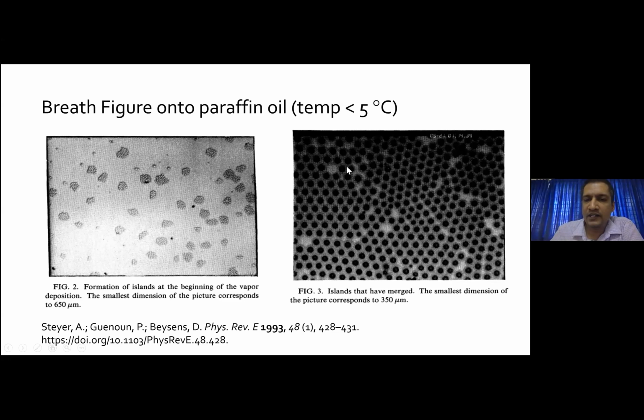The hexagonal patterns are not uniform at the grain boundaries. So this is the first observation. The observation is the islands are growing and they have the tendency to merge, but you can see the island's boundary even after the merging process is completed and so on. So this is one of the very earlier examples of capturing the droplet condensation even after the droplet has evaporated.